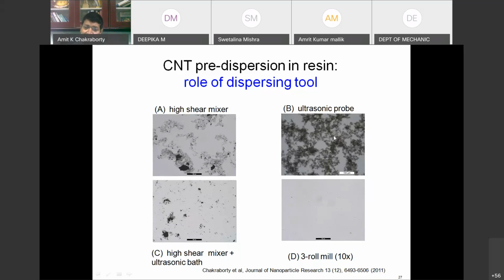You can see that the dispersion of carbon nanotubes in this is better than the previous two, but it is still not good because we are still able to see dark particles. If you see dark particles under the microscope, particles which are supposed to be nanoparticles, you are not supposed to see them at all at the microscale. The scale bar is only 100 micron. The fact that we are seeing them means there are still agglomerates. They are not nanoscale. These are agglomerates of particles which have micron size.